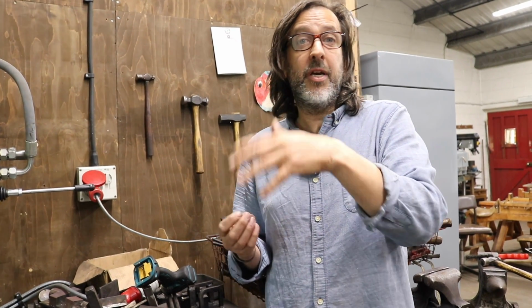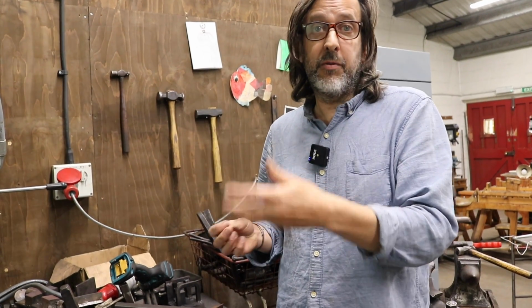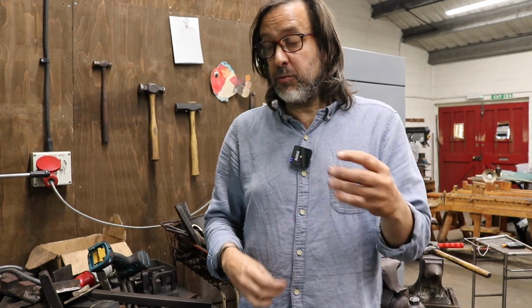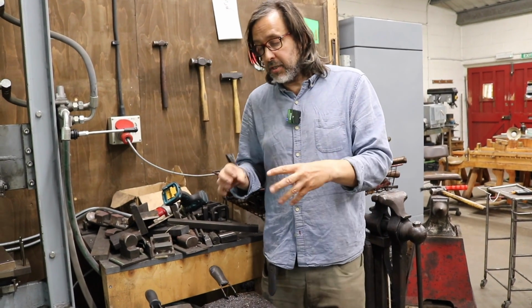If you test the hardness after an hour, the steel will be hard, but it won't be as hard. You might come up to, say, 60 Rockwell hardness, which is pretty good. Leave it overnight, and it might have jumped up another point or two, might come up to 62. Leave it another week, and it will come up to 62.5. It still carries on hardening over time. So that's why you've got this little window that you can actually hammer it, because it's sort of an exponential hardening. Obviously it slows off, but there's a little window when it hasn't hardened, but it's hard like glass.